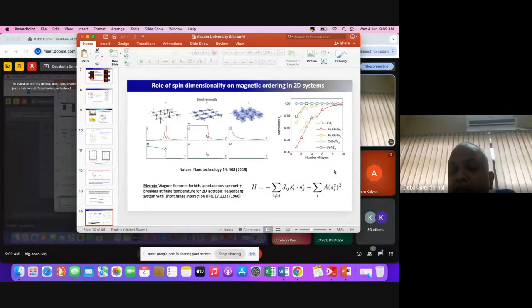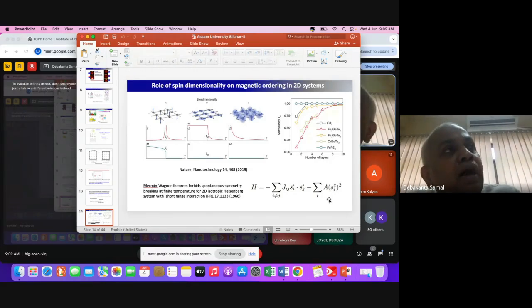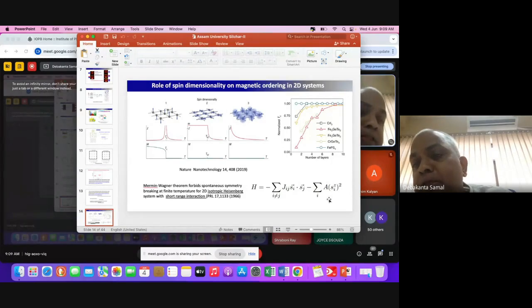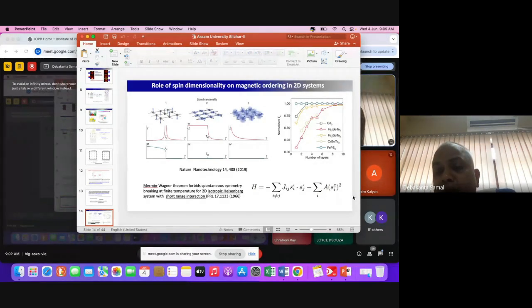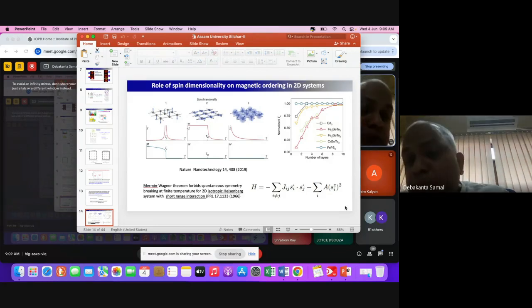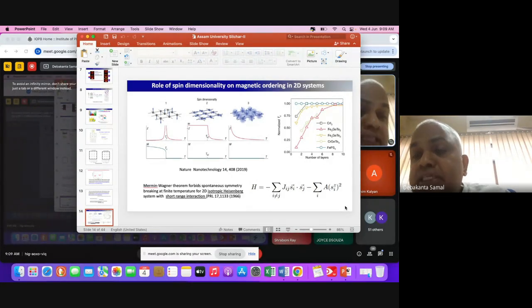Because in this kind of material, you introduce anisotropy in your Hamiltonian. The first term is the isotropic exchange interaction, and the second term in the Hamiltonian is your on-site anisotropy term. So if you put in anisotropy, people have found that it can show a kind of magnetic ordering. Why? The isotropic Heisenberg exchange interaction does not show any ordering at finite temperature because there will be excitation of magnons, spin wave excitations, that will kill the ordering. But when you put this kind of anisotropy in your Hamiltonian, or the system has some magnetic anisotropy, it could be on-site anisotropy or inter-site anisotropy, then it will be difficult for the spin excitations. So that's why you can restore magnetic ordering in a system, though it is a Heisenberg system, if you have anisotropy.